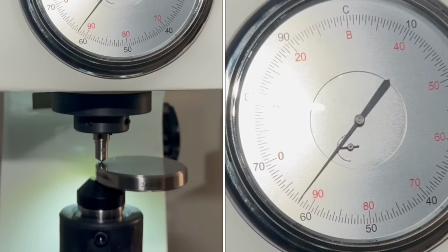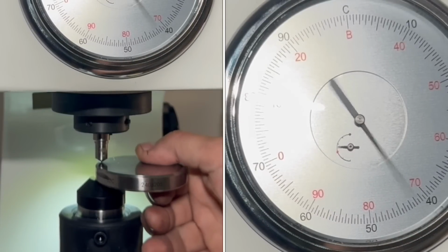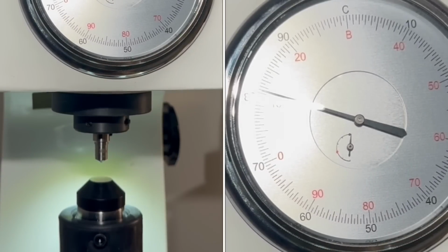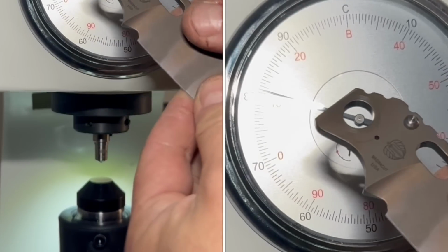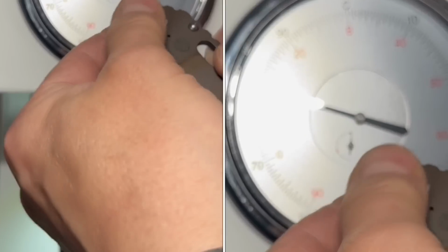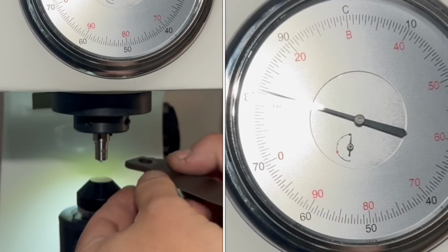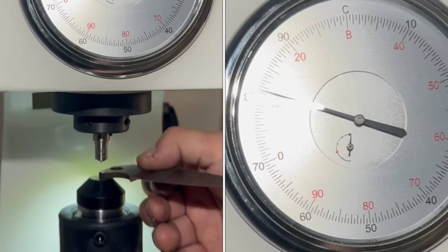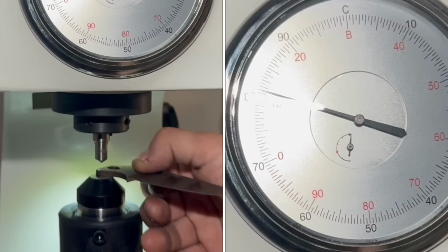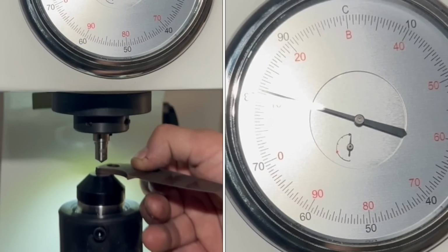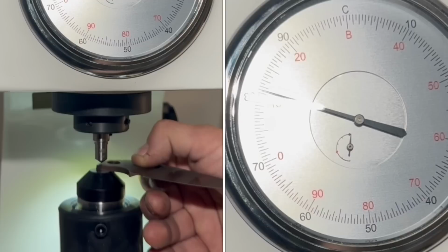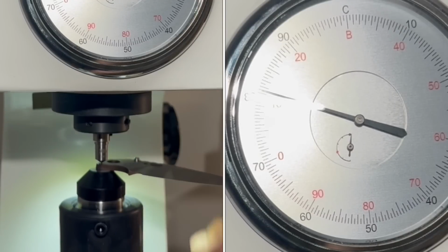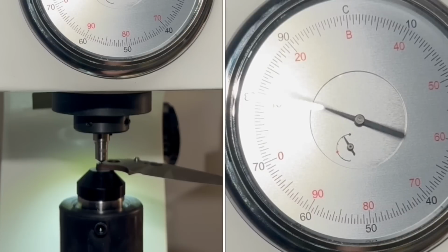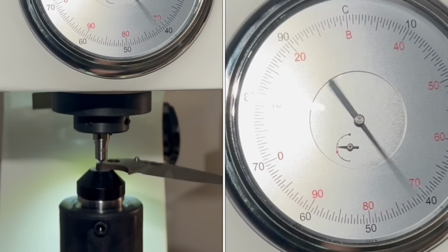This blade is made out of MagnaCut, which is a jack-of-all-trades stainless steel due to its highly balanced performance in toughness, edge retention, and corrosion resistance. The typical range for MagnaCut is 60 to 65 HRC. On the lower end of the range, between 60 and 62, you will get the highest corrosion resistance, whereas between 63 and 65, you get maximum edge retention. Most manufacturers are trying to hit the 62 to 63 range.